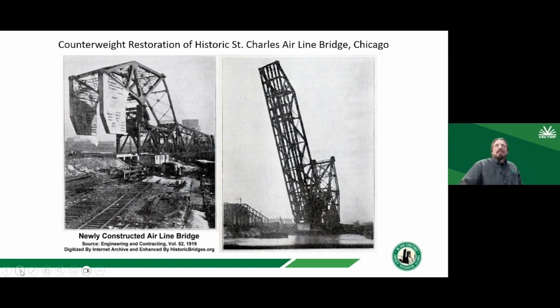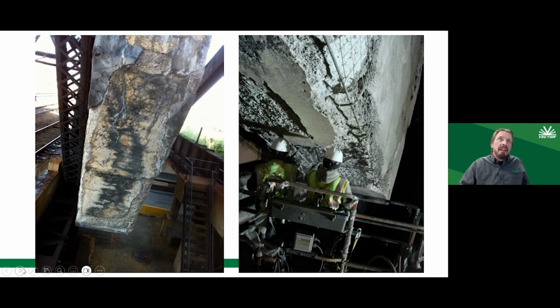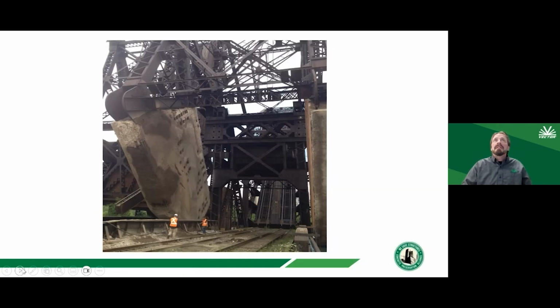The counterweight restoration in St. Charles Airline Bridge in Chicago. This is a bascule bridge. Again, a historic, old bridge, it had a very large concrete counterweight on one end of it so that they could raise the bridge. Over the years, freeze-thaw damage deteriorated a significant amount of the cross-section of that concrete. What they wanted to do on this one is rebuild it, restore it back to its original cross-section, and make sure that they had adequate weight to lift that bascule bridge again.